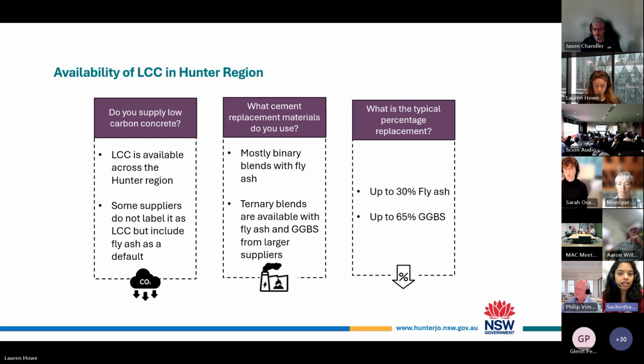Most of the suppliers provide concrete with fly ash, as I mentioned earlier, which means they are binary mixes with cement and fly ash. The cement replacement with fly ash is up to 30%. And the reason that they use fly ash mostly in Hunter region is we have a lot of coal-fired power plants in New South Wales, and fly ash is a byproduct of these coal-fired power plants. So it's easier for them to get fly ash and use that in their concrete mixes. But in Hunter region, we do have some suppliers, mostly larger suppliers, with both fly ash and slag in them, which means that they have ternary mixes with cement, fly ash, and slag. And we can normally replace a higher percentage of slag, and this replacement percentage goes up to 65%.